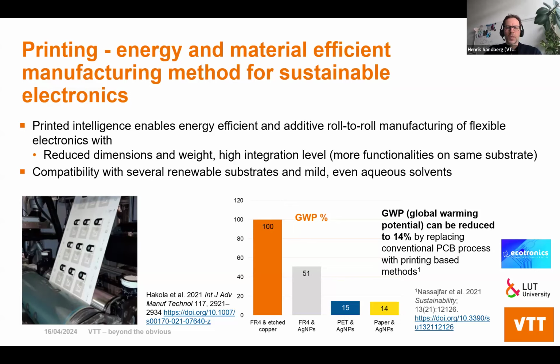solutions. If we look, as an example, at a printed circuit board, the conventional process relying on FR4 and etched copper, if you use that as a reference, just by changing the etching process of copper to printing silver nanoparticles, we can halve the global warming potential. And if we also get rid of the FR4 and use a very common plastic film like PET as a substrate, we further decrease this potential by down to 1/3 of the silver nanoparticle on FR4. So these are really huge differences.